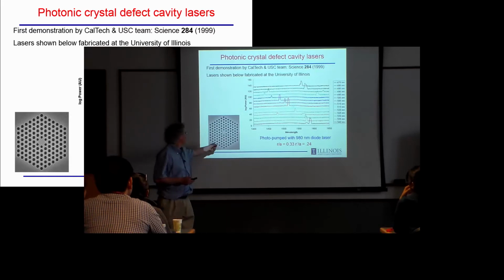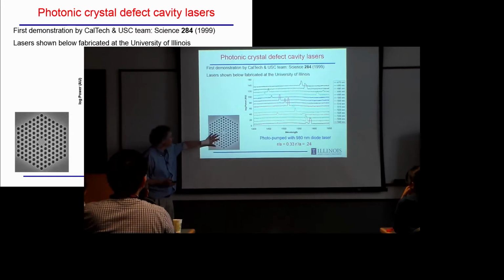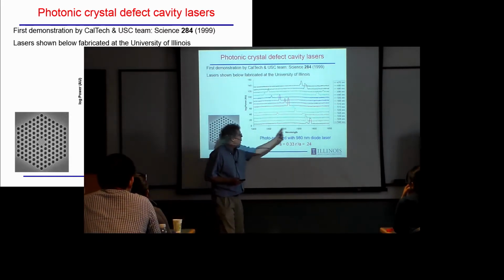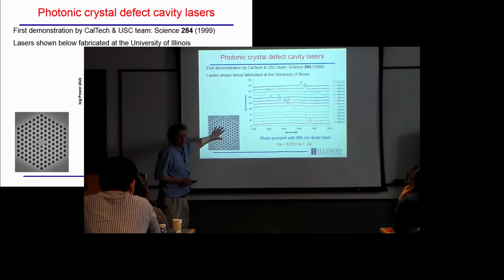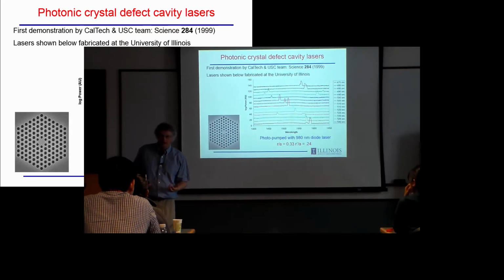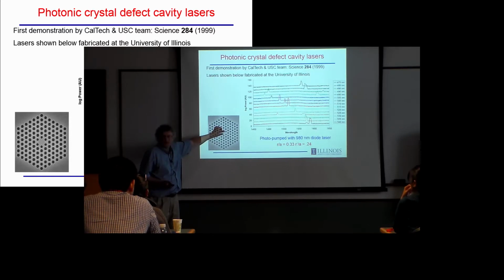So here are some photonic crystals that we've made in my lab. This allows us to tune. This is wavelength, and these lines here correspond to the light that's being emitted. We can tune this basically by controlling the size of the structure. This is now allowing us, as a nanophotonic engineer, to design what sort of structure these things can emit, and the light is being emitted from a region here that's a couple hundred nanometers.